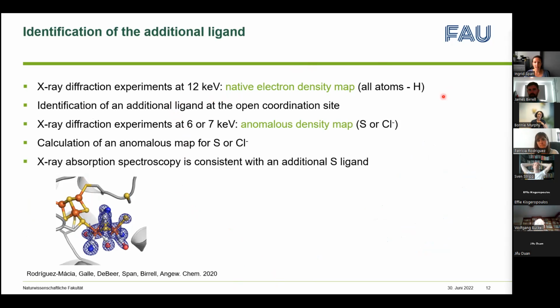So this is all atoms minus the hydrogens. And this map allowed us to identify an additional ligand at the open coordination site. But we don't know anything about the nature of this additional ligand. So then we collected an X-ray diffraction experiment at 6 and 7 keV, and this enables us to determine the anomalous density map. And at this energy, only sulfur or chloride ions are possible elements.